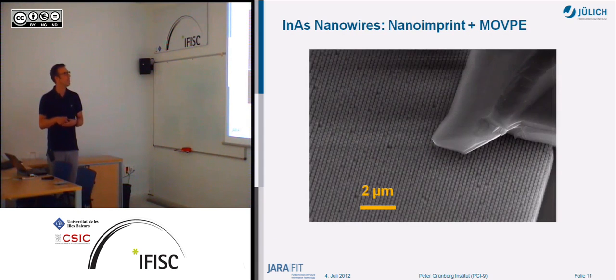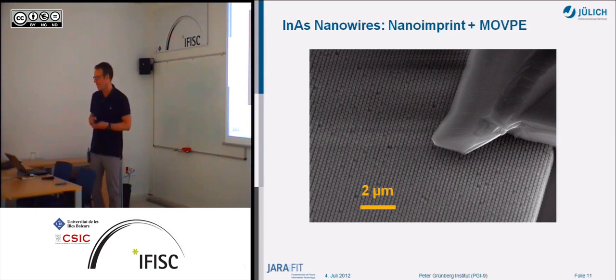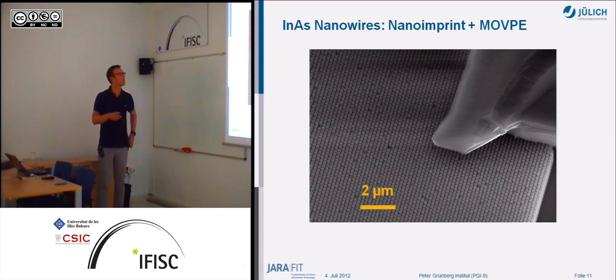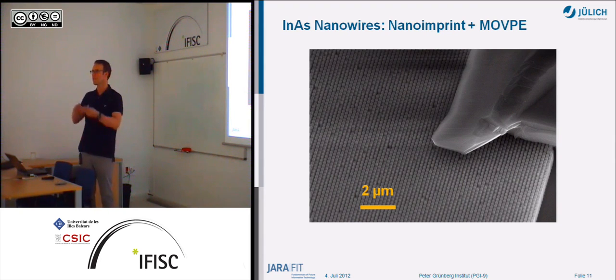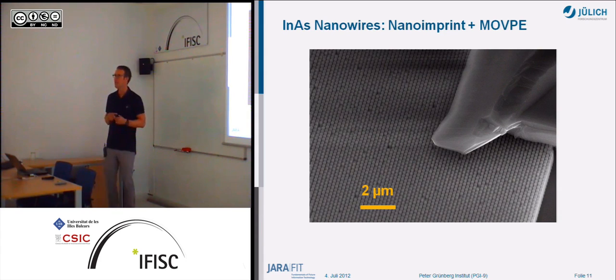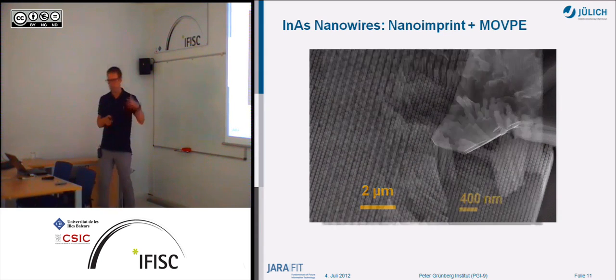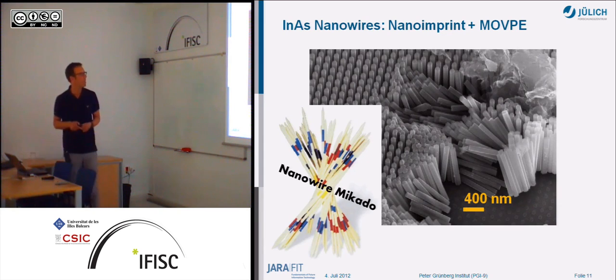Here you see a field of nanowires, and if you look closer, you see that you have really densely packed nanowires. This is a special method we're using. This is nanoimprint, where you can use a print method to make a whole field of holes in the substrate in one instant, and then you can grow the nanowires. So this is a very effective method to fabricate nanowires very quickly, let's say in one run with lithography.